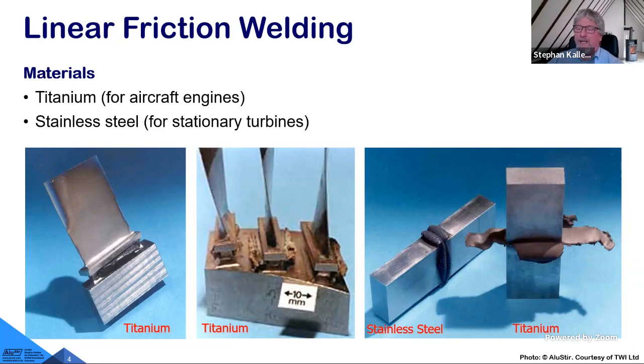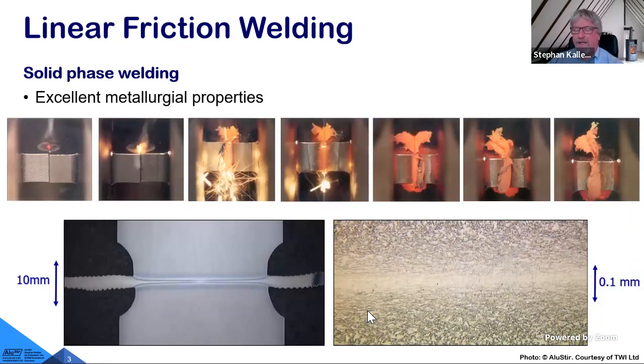And the way to do that is that we use a reciprocating motion while pressing the parts together with a very high force. Here you see some titanium being welded from the left to right. You see initial contact, and then a flash or burr is being expelled. And finally, the material cools down.